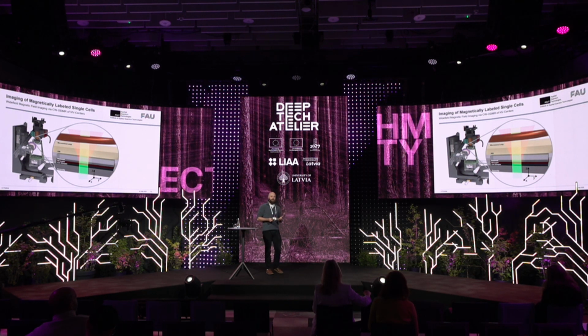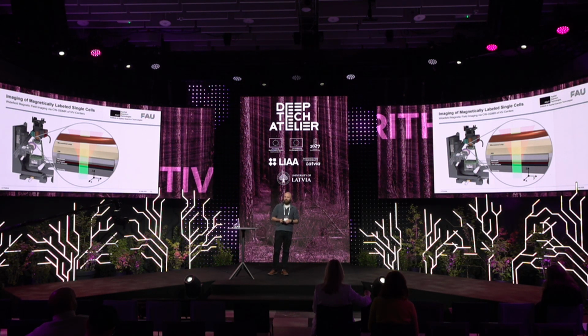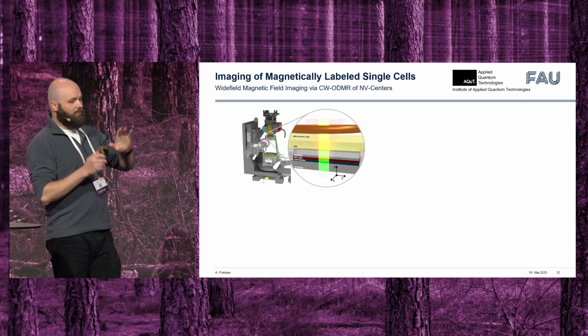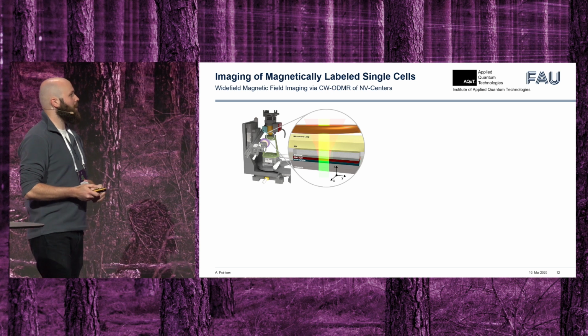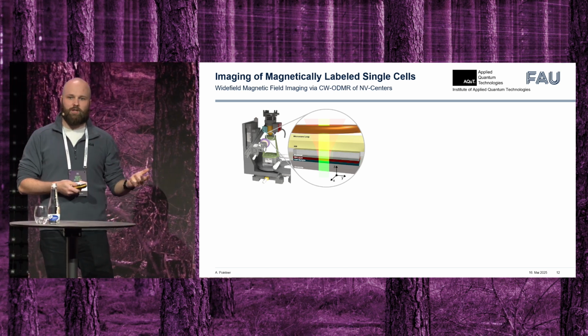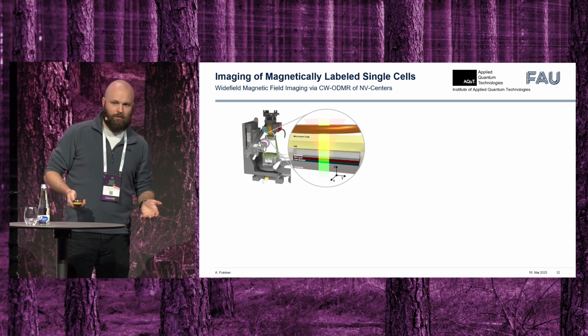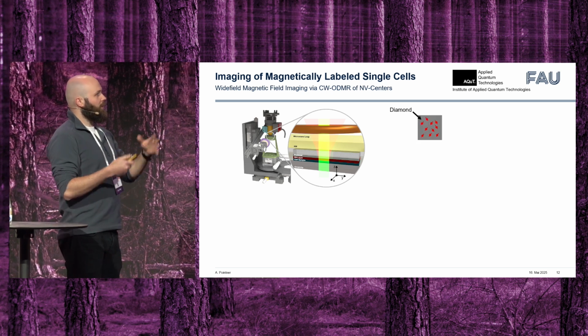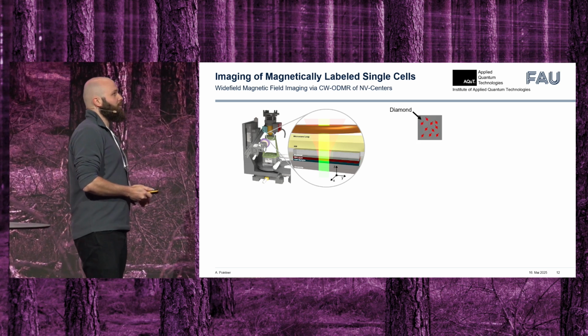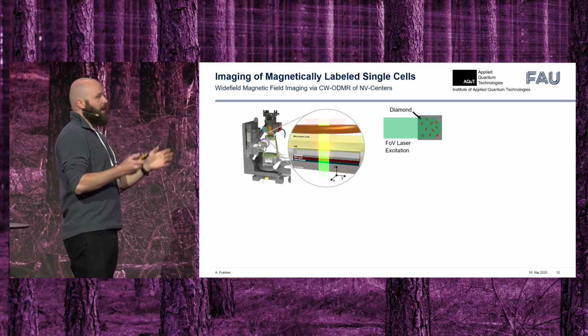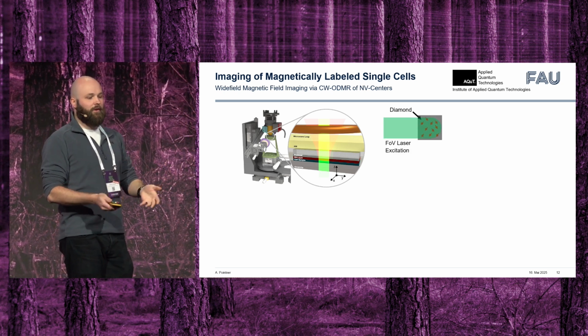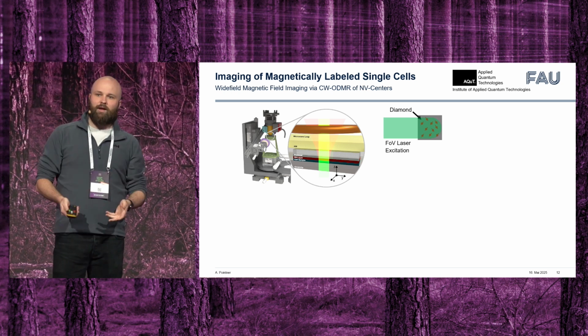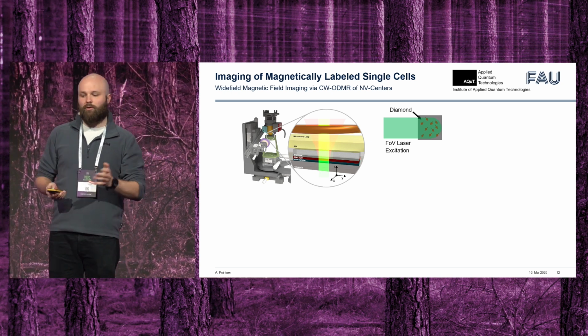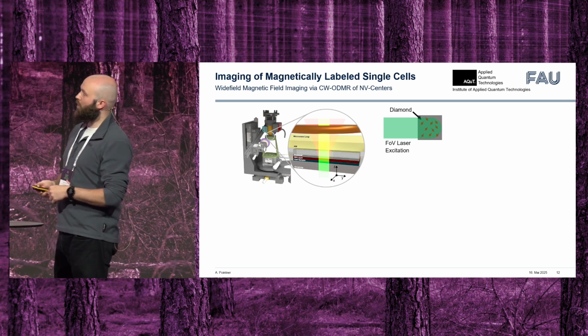So we bring our cell sample with these magnetically labeled cells in close proximity to our magnetic field sensor, and we perform a measurement. And I try to keep this short to give you an elementary understanding of how these measurements are and how easy they are at the end of the day. We use our diamond with our NV centers implanted on one surface. We excite it with a green laser so that we excite our spin system, which then decays and emits a red photon. And these red photons is what we can detect with our camera.